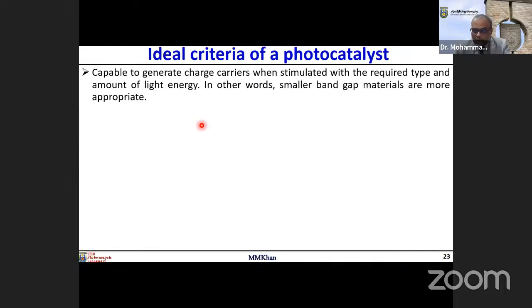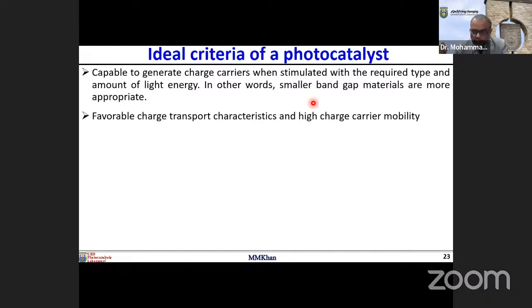So, the ideal criteria of the photocatalyst: it must be capable of generating charge carriers. That is very important. If you're using any material and it cannot create the charge carriers, then it will be useless. So it should be capable of generating charge carriers when stimulated with the required type and amount of light energy. In other words, smaller band gap materials are more appropriate in general. Why? Because if the band gap is very large, then you need very high energy like UV light or even stronger light. So if you have a photocatalyst that has a narrow band gap, whose energy lies within the visible range, then you can use visible light, which is free.